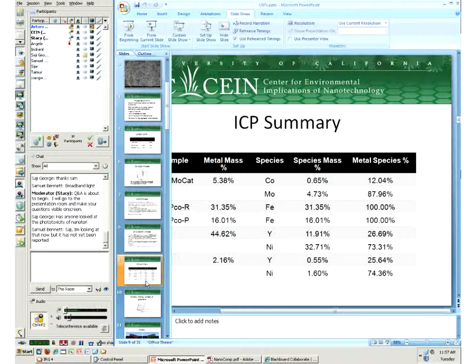So just to repeat the question as I understand it: for many of these nanomaterials, titanium dioxide, a lot of the metal oxides, some of the metals like silver nanoparticles, there seems to be a really small scale, the 1 to 20 nanometer effects, and then more bulk-like effects that you see at a higher size. Some people are trying to look at what that threshold is, and for those materials there seems to be a clear threshold. The question is whether we have a similar threshold for carbon nanotubes, and the answer is there's not enough evidence to show that there is a threshold for scalability.